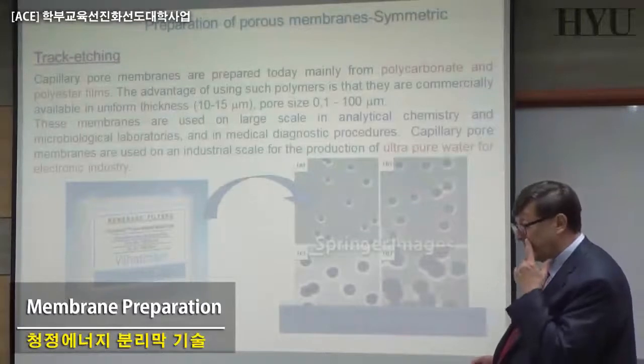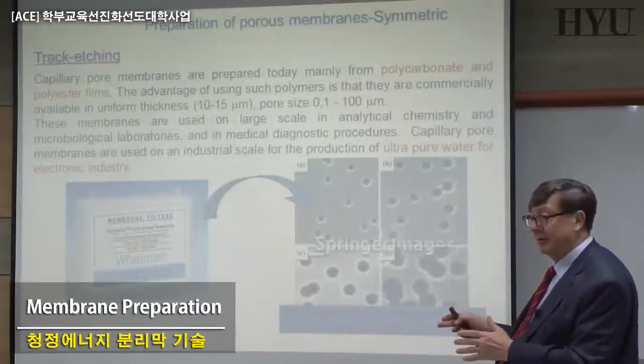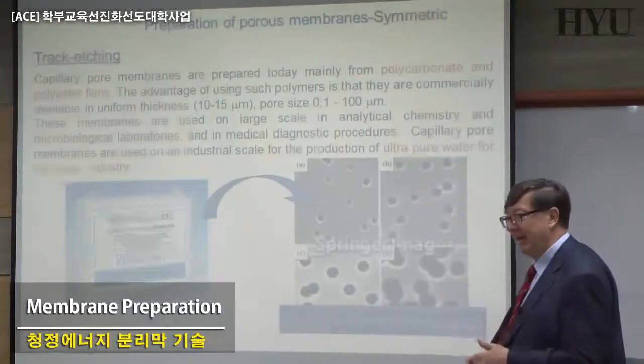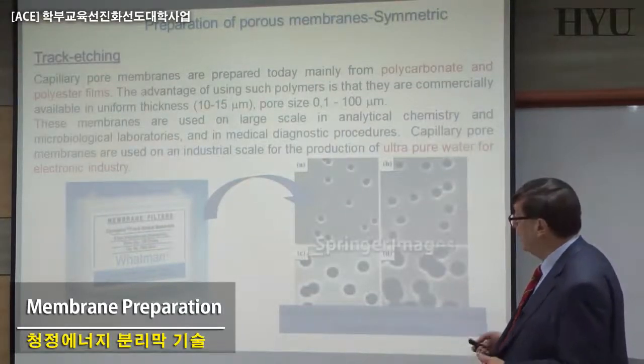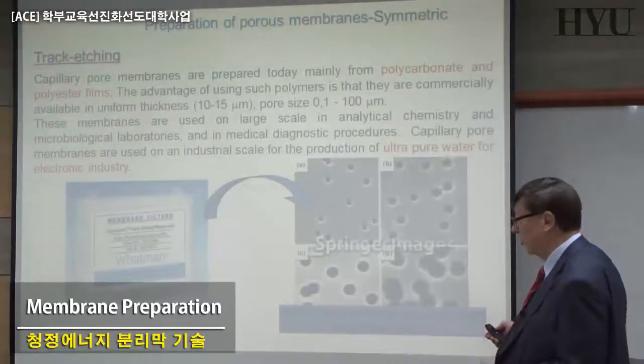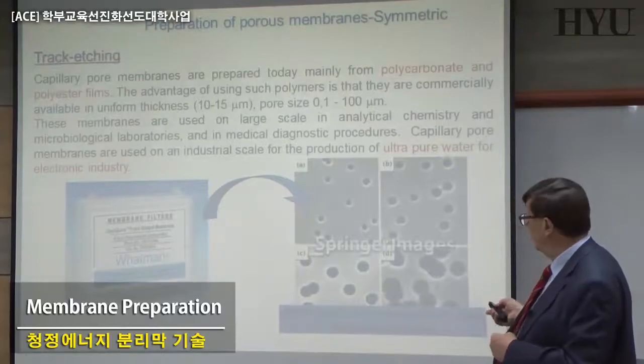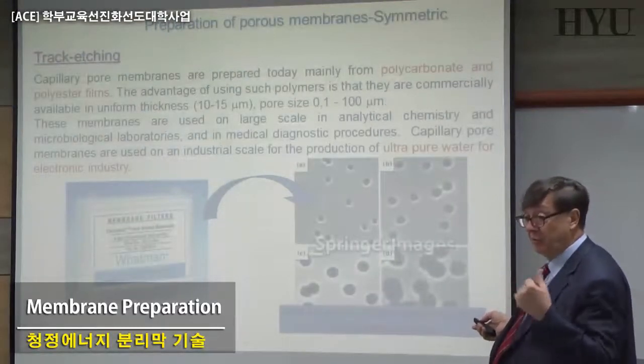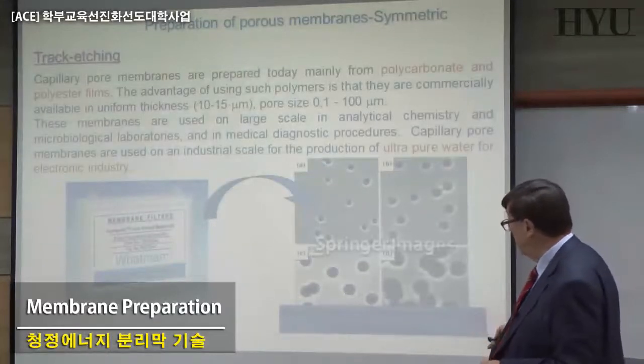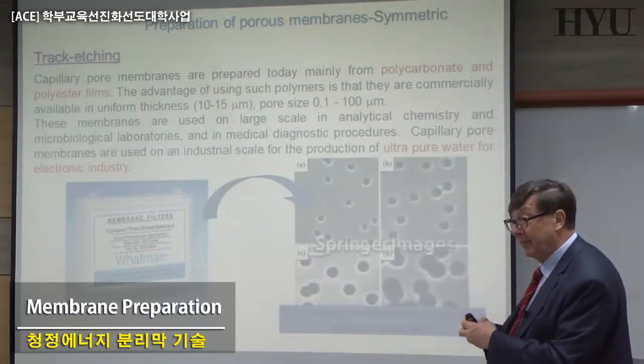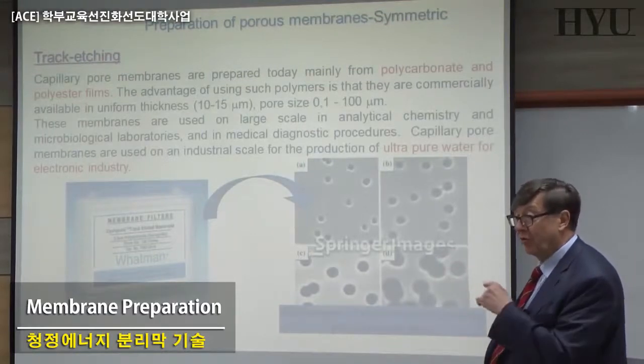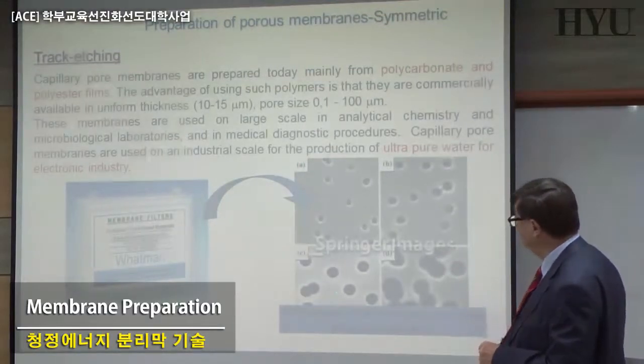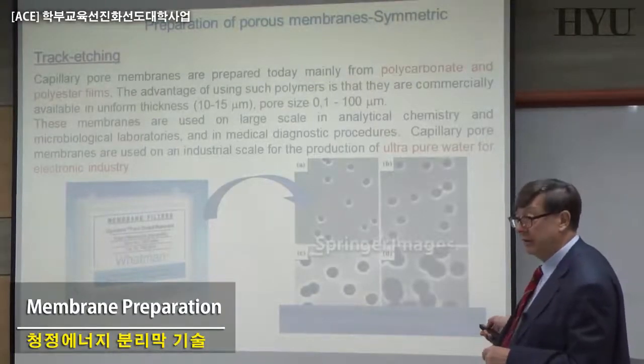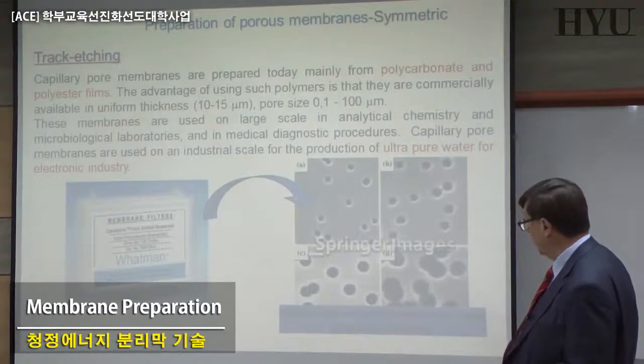That's quite interesting. Normally you buy these membranes just for lab scale or in a medical school, in biotech, etc. It's difficult to have a big module because of the cost, but interesting. As you know from before, we are trying to have the same morphology, eventually better, using phase inversion. And that's very elegant, and you have to avoid these kinds of problems. You see here that by etching, sometimes you have two pores nearby, and they merge into one, so it becomes a double pore. And that destroys the membrane for specific applications. So phase inversion can be well utilized for improving this kind of system. Not easy, but we are working exactly on this basically.